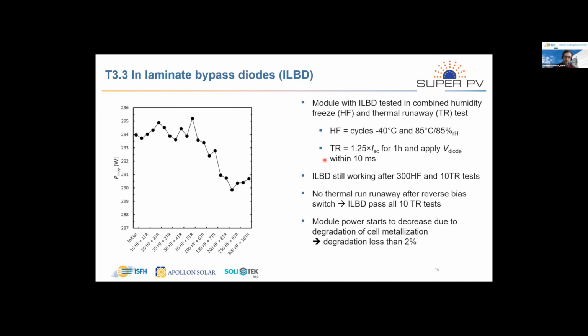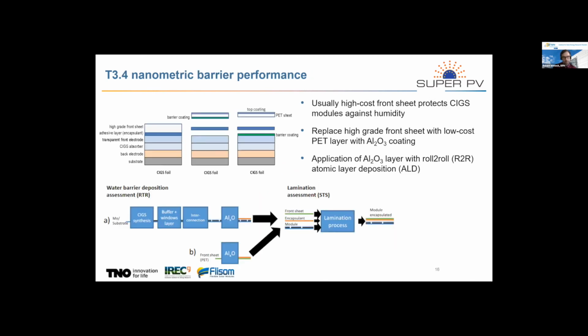This will result in a hot diode, and thermal runaway means that the diode becomes unstable due to this hot condition after 1 hour, and then further runs away and heats up until the diode will be destroyed. For our test, we have tested now 300 HF cycles and 10 thermal runaway tests, and we haven't seen any degradation of the diodes and only a small degradation of the module, which is less than 2% in this case. The last innovation is the CIGS barrier coating.